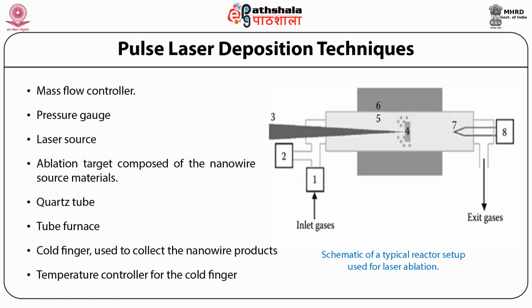Silicon nanowires have been produced using silicon iron targets with a neodymium yttrium aluminum garnet (Nd:YAG) laser, irradiated at 2 watt average power, 10 Hz pulse rate, and wavelength of 532 nanometer in 50 SCCM of argon flow, standard cubic centimeter per minute. The Si 0.9 Fe 0.1 target was ablated to create the source vapor, and the nanowires were deposited on the cold finger while the tube furnace was maintained at 1200 degrees Celsius. The resulting silicon nanowires were 10 nanometer thick and several micron long and consist of Fe-rich cluster at their tip.